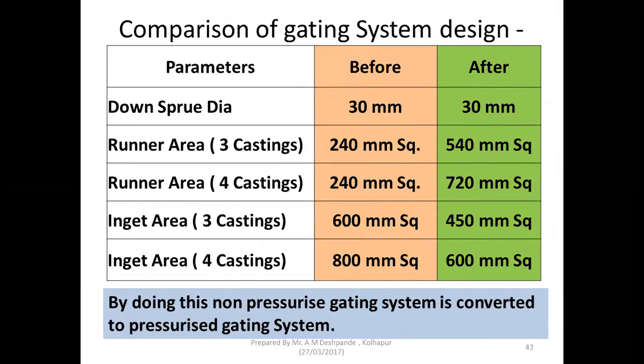That was the runner bar. Ingate area for casting 3, initially it was 600 mm square. Then I corrected it to 450 mm square because the weight of the casting is just 1.2 kg, which doesn't require more area. And in the case of casting 4, it is 600 mm square.